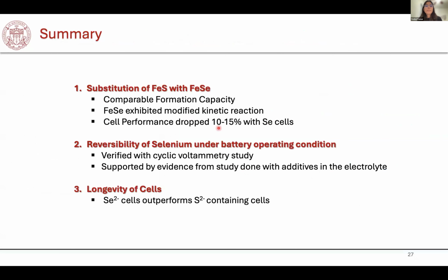And just to summarize the talk, the goal was to find an alternate additive that could serve as a depassivating agent without compromising the life cycle of the electrode, and selenium serves the right purpose for that. It was found to be electrochemically reversible. The performance of the iron electrode did not significantly change in terms of formation capacity or discharge rate capabilities, and the life cycle studies confirmed that selenium containing cells outperform the sulfide containing cells.